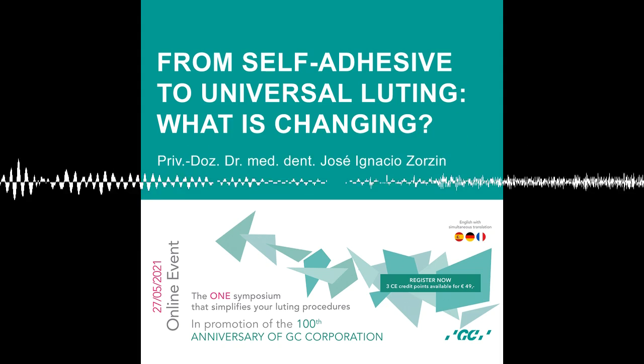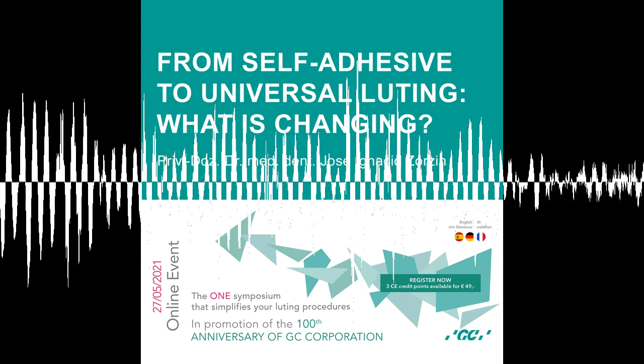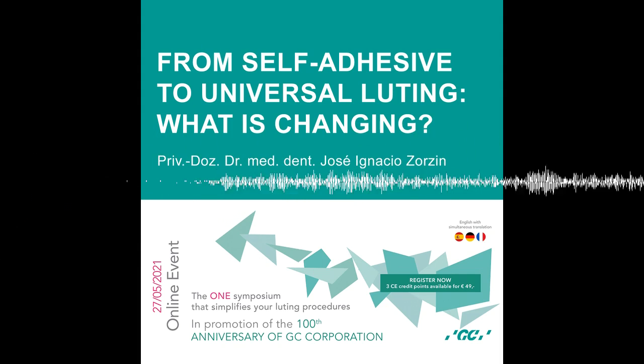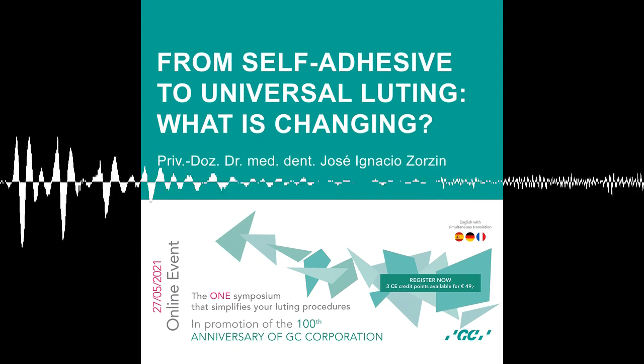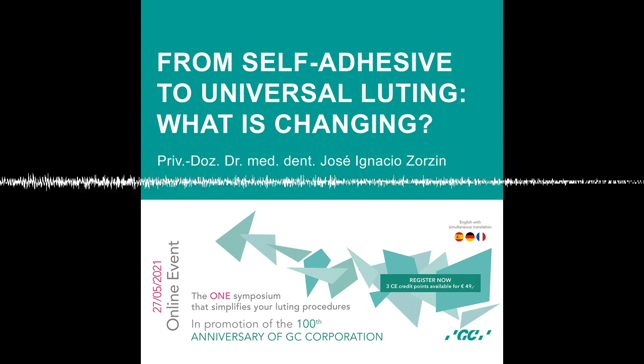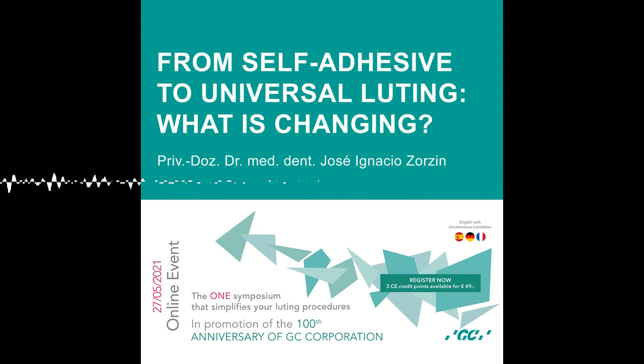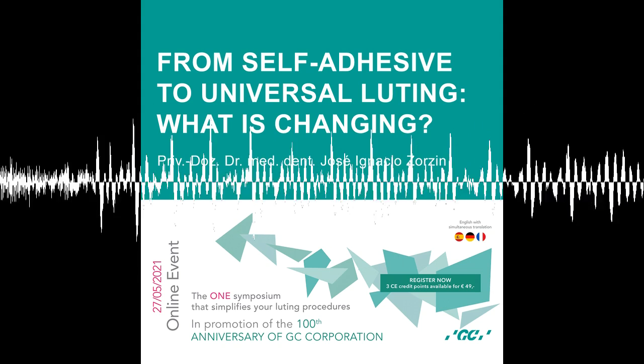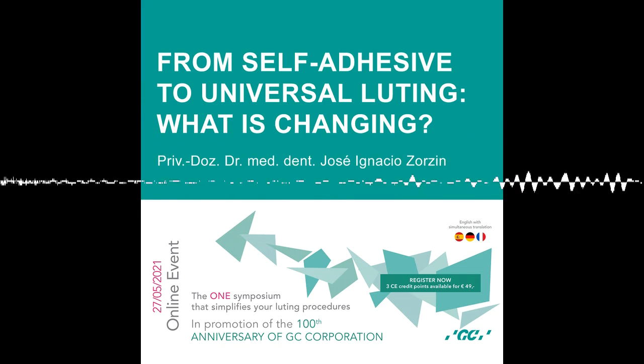But I think the most important thing really is to etch or do the proper surface pre-treatment for each material, and then afterwards put the proper primer, in case of glass ceramics, go for a silane, for example. That's the important thing. That maybe makes the difference, in my opinion. How long do you let the silane on the glass ceramic? Just this typical 1 minute after instructions?